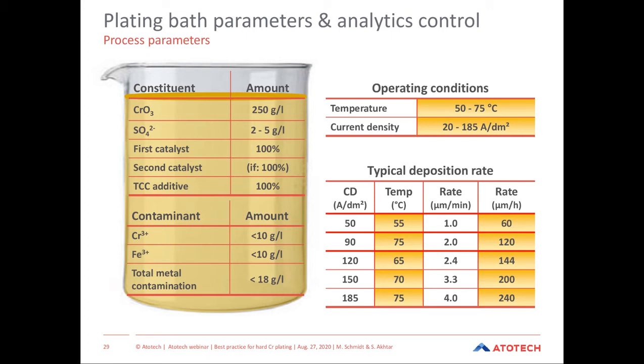On the left side, you see the typical components in chrome plating baths. We have chromic acid as the main deliverer of the chrome with an amount of about 250 grams per liter. A sulfate as the first catalyst, which is making the chrome plating possible in a first stage, between 2 and 5 grams per liter, depending on application. There can be several catalysts inside the bath. They should be operated, of course, at a level of about 100%.